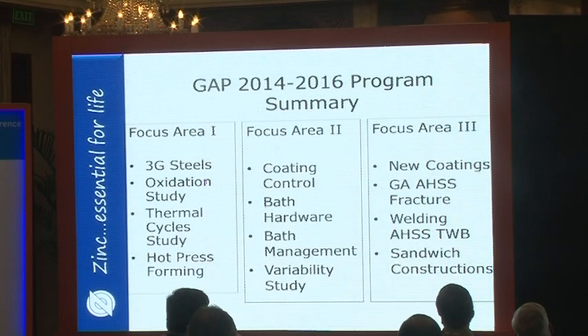We've heard about zinc aluminum magnesium several times, and we show here that you have lower levels of zinc aluminum magnesium skimmings with air wiping or nitrogen wiping. This is in the range also of that few kilograms per coil. You can't avoid that. We have to understand that. We have to manage that and make sure we are producing high quality coatings with this. So the GAP program is operating in three areas: the galvanizability of all these new steels, the improvements of the galvanizing line operations, and also the characterization of coatings and the development of new coatings.